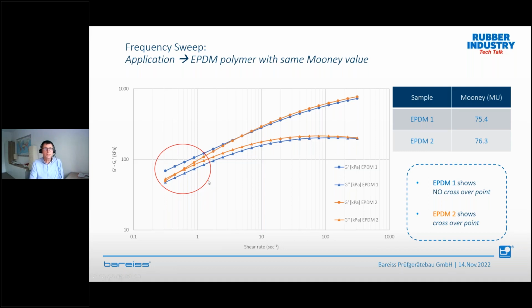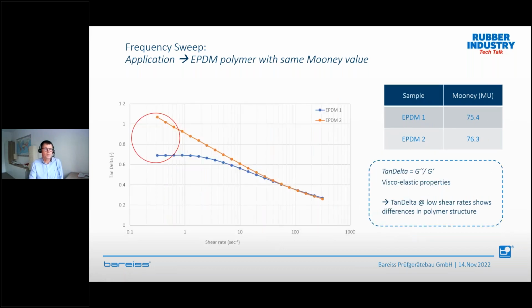Another indication of this will be the tangent delta. Maybe you heard of the tangent delta. The tangent delta is a calculation, a ratio between G double prime and G prime. So it gives you something about the elasticity, and it gives you something about the viscous behavior of the compound. I always call it information about your viscoelastic properties. And over here, when you go to a lower shear rate, you see huge differences in tangent delta. Again, both have the same Mooney viscosity.